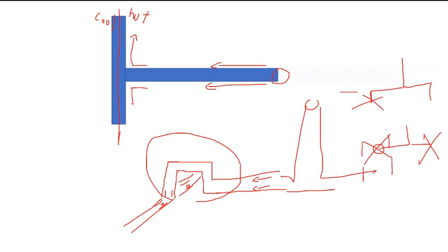Okay, the next one: a stress mark happens because of the sharp edge on the part or any other reasons. I would say in some cases, yes, the sharp edge on the part will cause the stress mark. But in the case I shared in case one, it is more caused by the temperatures. And yes, the sudden change of the thickness will cause the temperature difference. So it's related to the sharp angle edge, but most normally it is related to the temperature distribution and causes high residual stress on the part.